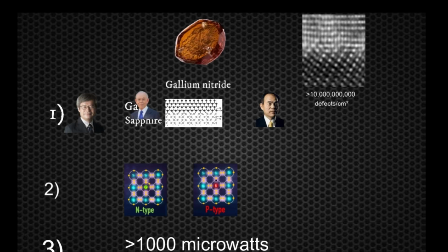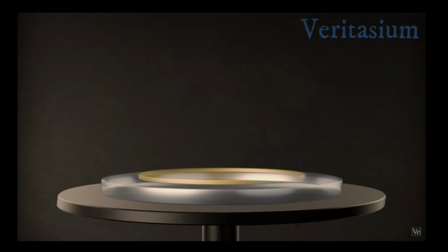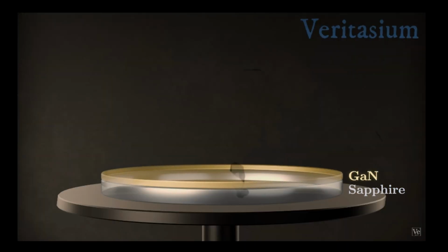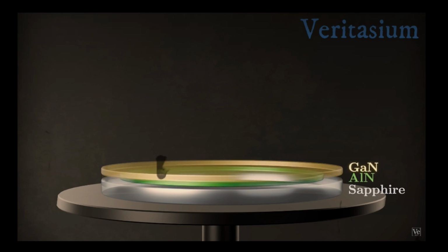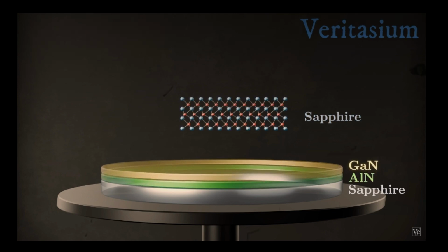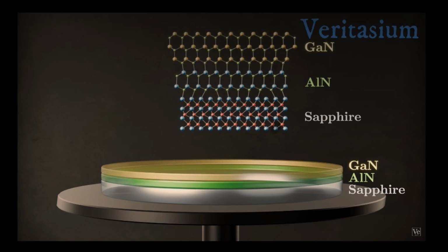A few years earlier, they had made a breakthrough on the first problem of high-quality crystal. Instead of growing gallium nitride directly on sapphire, they first grew a buffer layer of aluminum nitride. This has a lattice spacing in between that of the other 2 materials, making it easier to grow a clean gallium nitride crystal on top. The only issue was that the aluminum caused problems for the MOCVD reactor, making the process hard to scale.